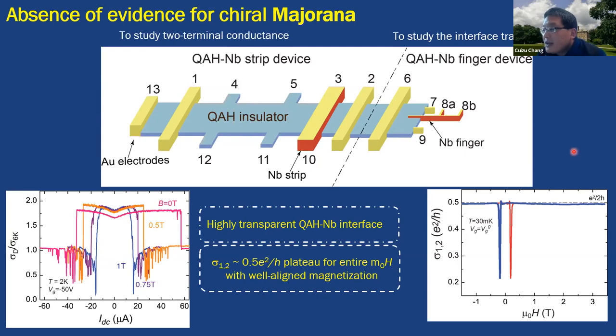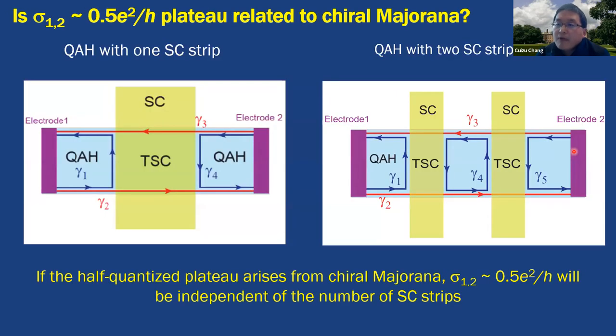to demonstrate whether this e squared over 2h is related to the chiral Majorana or not, we performed this control measurement. You know, this is the control measurement. So if we put one superconductor strip, you know, there will be four Majoranas formed, from gamma one to gamma four.